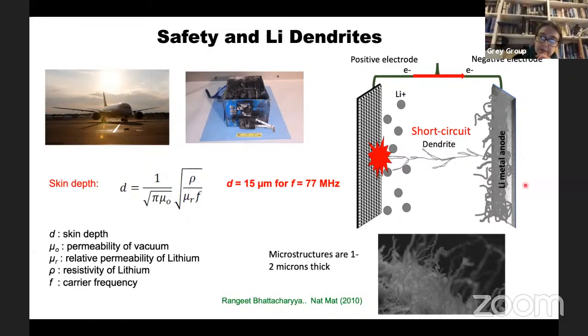If you do the same thing with graphite and you charge it too fast, you can also plate lithium and have the same problem. What we recognized a while ago was that the same issue you have about getting the RF through a can in a battery applies to lithium metal. So you can't just detect the full amount of the lithium metal, but you can actually detect these dendritic structures, and you can quantify how much you can penetrate the RF through via the so-called skin depth effect.